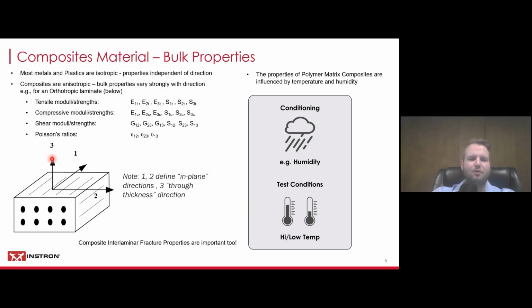And then there's also direction number 3, which is considered the through thickness direction. So directions number 1 and 2 are typically defined as the in-plane directions, and direction number 3 is the through thickness direction. And as you've seen in the previous slide, you usually have multiple plies that get laminated on top of each other, and that's how you end up with your composite, which is also the reason why the interlaminar fracture properties are very important for composites, because you laminate them together. If there was a crack or other failure, a void or something like that in between, you need to know how much residual strength is in your composite. So it's not just the normal tensile, compression, and shear. There are a lot of other test types which we'll get to.